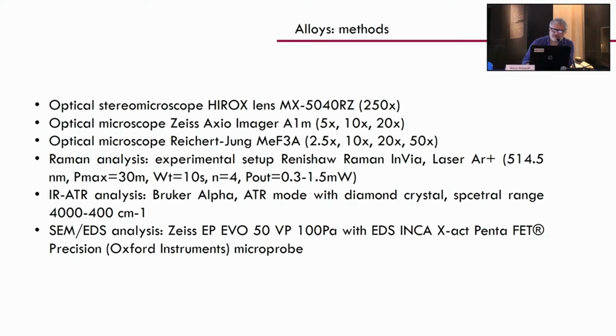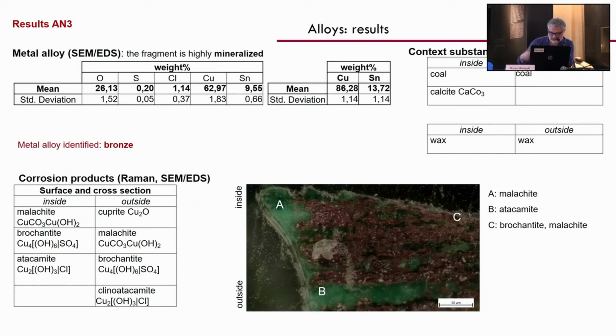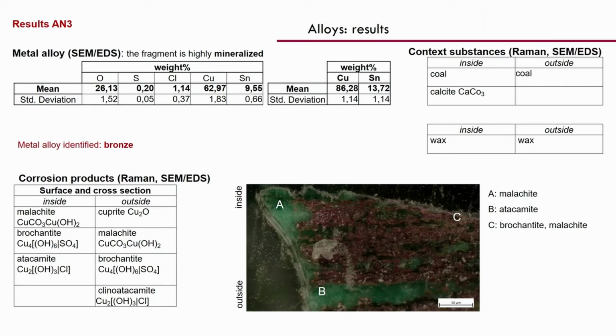And what we found was a very interesting situation, with some cases that are going to be analyzed, and with some questions. So the first sample, as you can see, we found copper and tin in a high percent weight, but this, as almost all of them, is totally mineralized. So we totally lost the metallic alloy. It was completely mineralized. And here you can see all the phases that you can find in this kind, so malachite, cuprite, and so on.